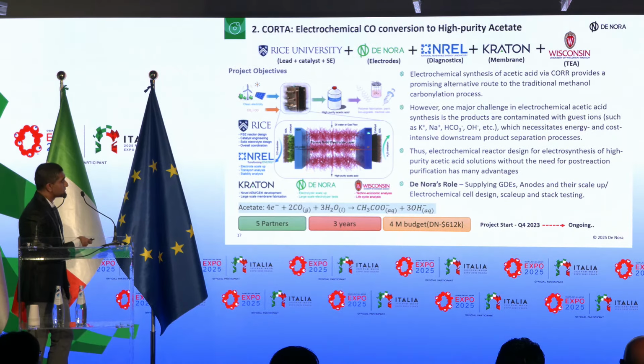What you see, starting from the anode side, is very similar to a PEM water electrolyzer. We have an anode with the precious metal catalyst, then a cation exchange membrane, and then something called the porous solid electrolyte layer. Next to the porous solid electrolyte layer, we have an anion exchange membrane, and then a de Nora gas diffusion electrode with a catalyst which can convert carbon monoxide to acetate. This acetate is going to cross the anion exchange membrane and come into the solid electrolyte layer. Protons come from the anode side, and they combine. Then you can use deionized water or humidified gas flow to pull out the high purity acetic acid.